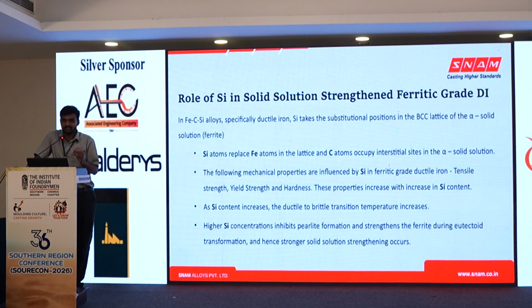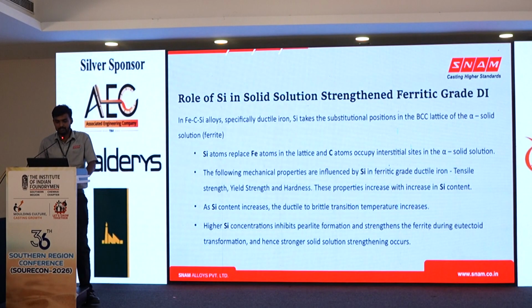As the silicon content increases, the ductile to brittle transition temperature also increases. The higher the silicon percentage, it will suppress the pearlite formation and promote ferrite formation in the eutectoid transformation, and hence make the material stronger.